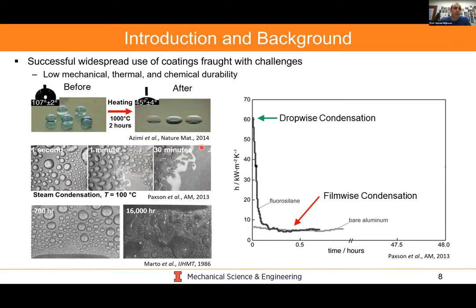And this is actually degradation of the surface due to some mechanism, which up until maybe 5 or 6 years ago was unknown. If we look at polymer films, it's the same thing. We start seeing blisters form, as I showed you in the previous image. And after about 16,000 hours, we lose the dropwise condensation.